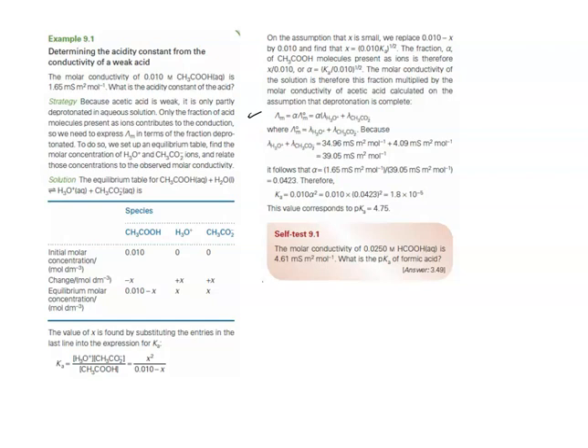And so it follows that Ka will equal 0.010 alpha squared, where alpha is 0.0423, and we can find that the value corresponds to a pKa of 4.75, which is the pKa of acetic acid.